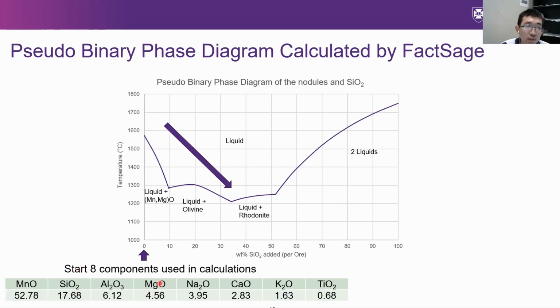Then we use silica as a flux and calculate how the liquidus temperature changes with the addition of more silica to the nodules. As we can see, this is the liquidus line. Above this line, the slag can be operated in the fully molten state. With the addition of silica, the liquidus temperature dramatically decreases. However, we cannot add as much silica as possible, because we also need to consider the viscosity of the slag, since silica actually increases the viscosity of slag.